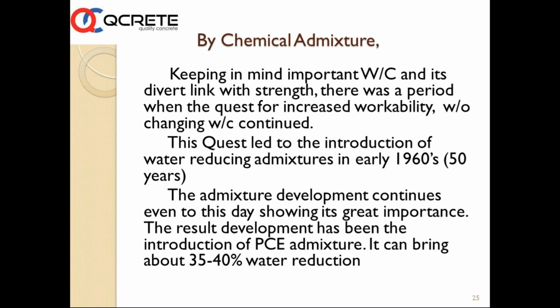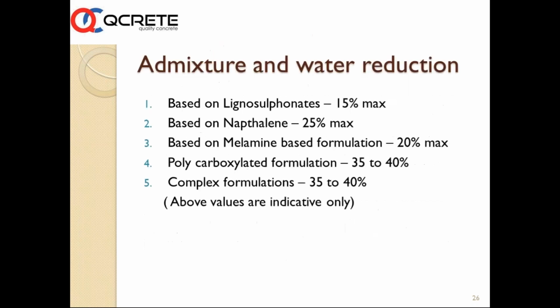So from the 1960s up to the recent one, PCE admixture, which is one of the recent ones, brings quite a lot of reduction in the amount of water. Lignosulphonates were the first to be used, so they can go up to 15% maximum reduction in water. Next is the next generation, naphthalene and melamine. One was giving 25% maximum, the other was giving 20%.